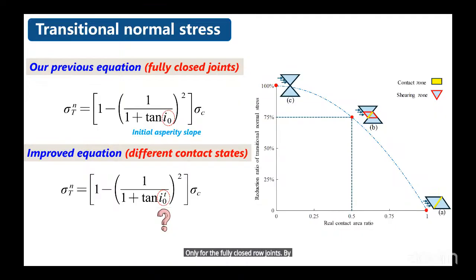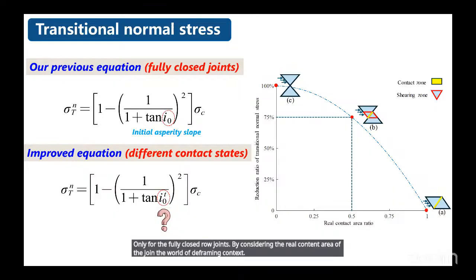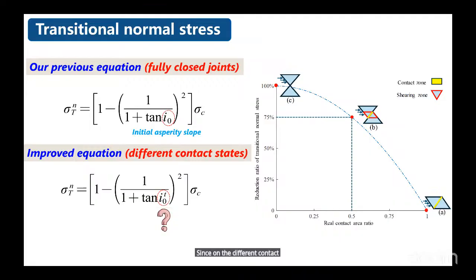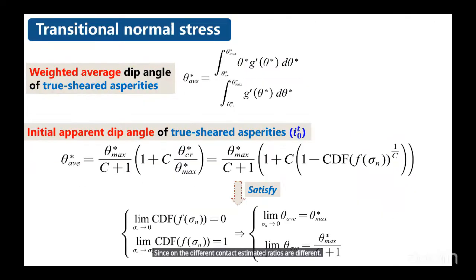By considering the real contact area of the joint walls in different contact states, here we show an improved equation where the initial asperity slope is replaced by the initial slope of the truly sheared asperities, since in different contact states, the asperities truly sheared are different. To determine the initial slope of the truly sheared asperities, we use the concept of the weighted average dip angle that quantifies the relative contribution or density of the asperities with dip angles higher than the peak dilation angle. Then the derived equation of the initial dip angle of the truly sheared asperities can be predicted by the 3D morphological parameters and the real contact area ratio. When the normal stress is 0, this initial asperity angle is the maximum. And when the normal stress arrives at the transitional normal stress, this angle is the average value of all the asperities.